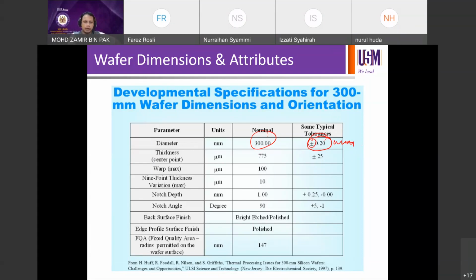So say if you are using 775 micron thick wafer thickness, and then you can only afford a variation of 25 micron plus minus. Okay, so warp, this is the surface warp. I'm going to show you later on the real specification online. So you can only afford up to 100 micron, and then thickness variation, total thickness variation, we call this TTV usually. I'm going to show you soon online. So you can only afford a variation of 10 micron across the wafer surface.